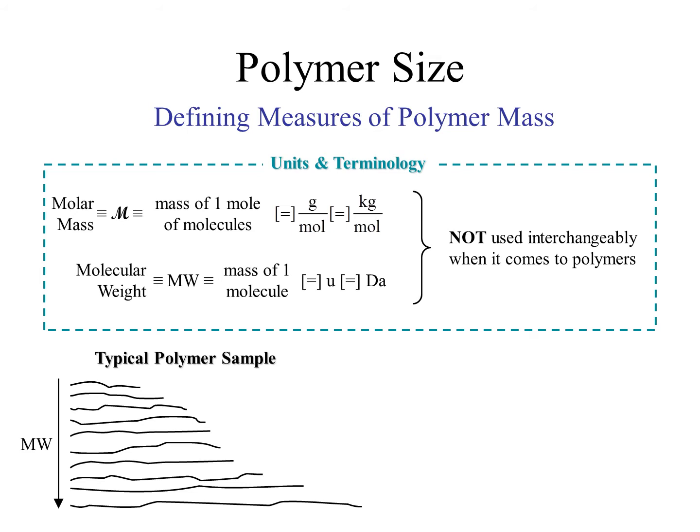If I were to ask you for the molar mass of this polymer sample, you would need to figure out how much a mole of these polymer chains would weigh, right? Okay, you could do that, but does that molar mass actually describe every polymer molecule in the sample? No, it wouldn't. It would actually be some sort of average. The problem is that we have a distribution of chain lengths here. Thus, we have a distribution of molecular weights, which leads me to that definition.